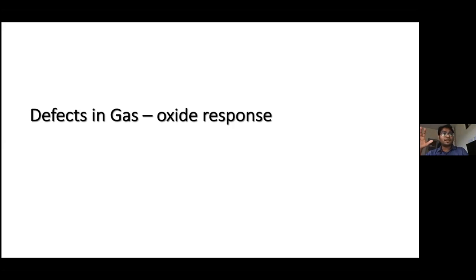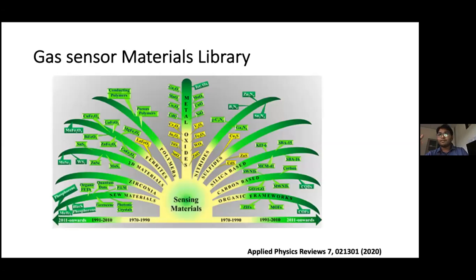So the first one, just to get acquainted with this idea of gas sensor materials, these are nothing but semiconductors whose conductivity is basically changing with the ambient atmosphere gases. Some of the gases like oxygen are basically electron trap states. I mean, they are electron acceptors. So when oxygen gets absorbed, it reduces the carrier concentration. If there are gases like hydrogen, it donates an electron and it will change the carrier concentration in the opposite direction.